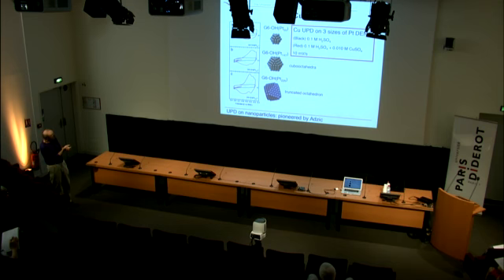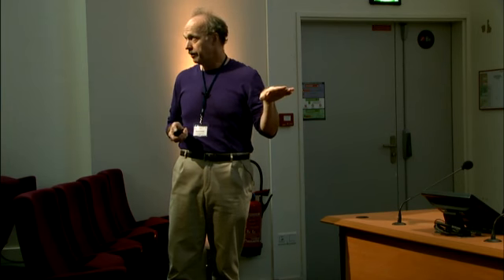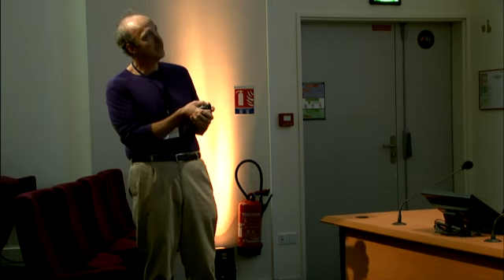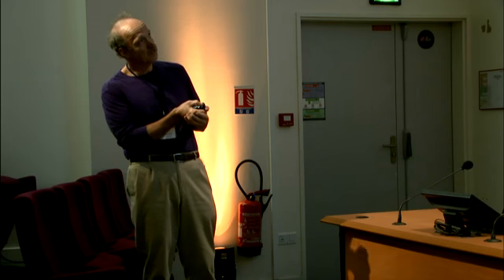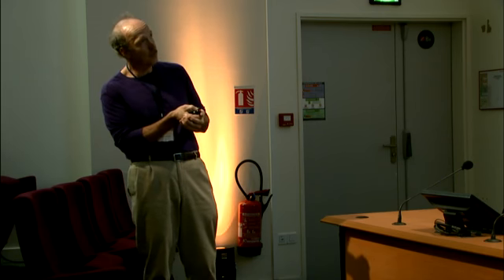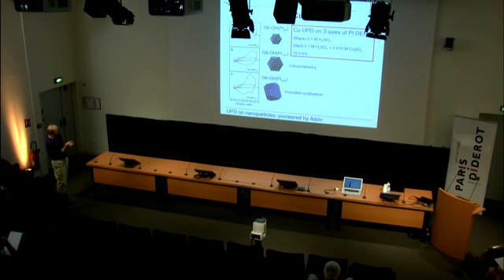The black is always the background scan, which is a scan of just the platinum dendrimer-encapsulated nanoparticle in an electrolyte solution, but with no copper added. So it's just the background. Okay. Now you add a little bit of 10 millimolar copper and do a scan. That's the red here, and you can see here's the deposition of a monolayer, we think, of copper on this little particle, and then this is the stripping of the copper from the particle.